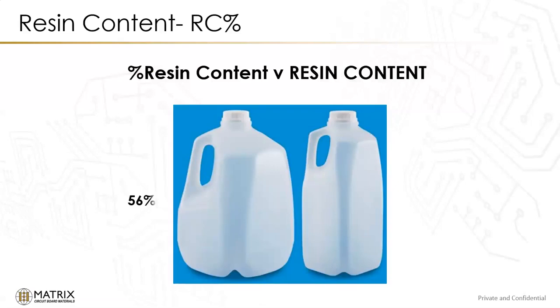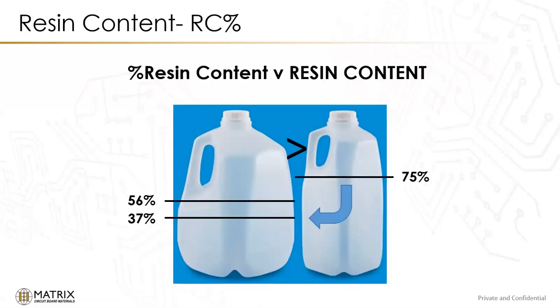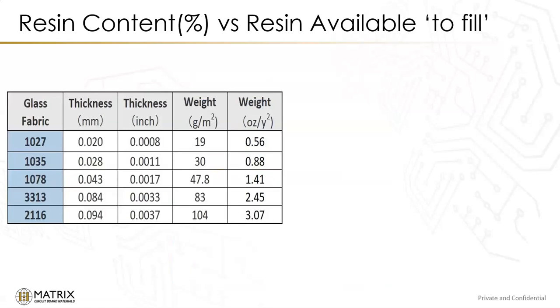So if we happen to have a 2116, maybe it's 56%, and we compare that to a 75% 1035, which one has more resin? Which one has more in the container? Well, we know the container size, so we know for sure that the gallon product that has more than half definitely has more than the half gallon less than full. So if we were to relate that, what does that really mean? If we take the 75% of a half gallon, it really equates to 37% if we're looking at the same container. So it's important to know what the container size is, or what your glass weight and glass thickness are, to be able to help predict what you need for fill or what the best option would be for thickness and fill.